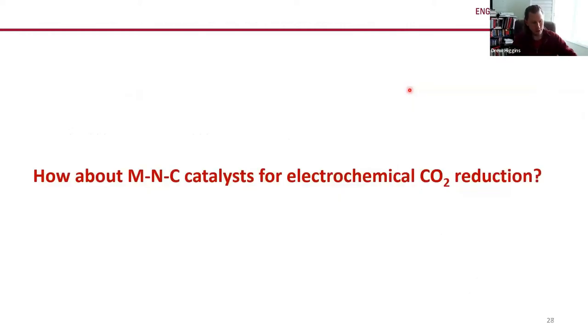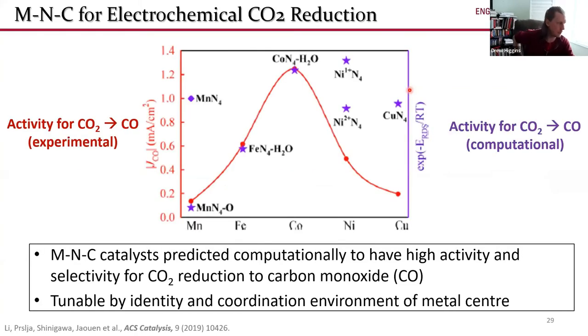So I've talked about iron nitrogen carbon catalysts for fuel cell applications, but how about these metal nitrogen carbon catalysts for electrochemical CO2 conversion? The big question was, can the same type of catalyst be used for CO2 reduction? And the answer is yes. A couple of years ago, there was some very nice work doing a combined computational and experimental study that found that many of these transition metal nitrogen carbon catalysts could be very selective for the conversion of carbon dioxide into carbon monoxide. The activity varied quite significantly based on the type of metal used to prepare these catalysts, because obviously the identity of that transition metal doing the catalysis is going to have a big impact on the activity and the selectivity of these materials.